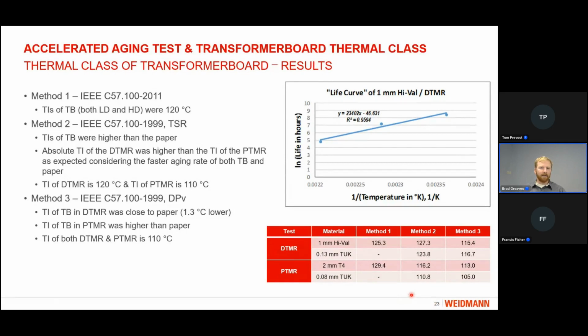The absolute thermal index of all of these materials for the distribution ratio was, again, 120 degrees C, rounding down to the nearest 10. And for the power ratio, rounding down, was 110 degrees C. We can make sense of the results from the distribution ratio being higher than power based on the aging curves that we saw previously, in that the power ratio ages much faster than the distribution ratio. So when we look at the same end-of-life criteria for both ratios, in this case 50% tensile retention, we would expect that the power transformer materials ratio would achieve that end-of-life criteria quicker, in turn resulting in a lower thermal index than the distribution.